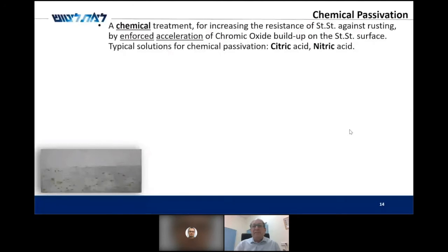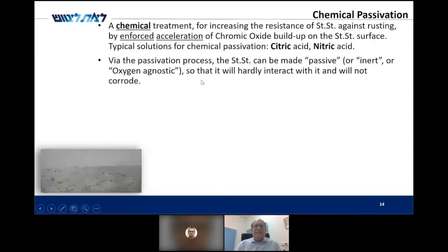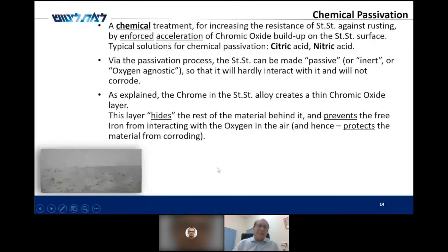So let's talk about chemical passivation. It's a chemical treatment for increasing and speeding the resistance of stainless steel against rust. We enforce the acceleration of this chromic oxide buildup using two classical acids, a very weak acid called citric acid and a strong acid called nitric acid. This passivation causes the stainless steel to become passive or inert or oxygen agnostic, so it will hardly interact with the oxygen in the air and will not corrode. And as I mentioned earlier, this is the generation of the chromic oxide. It hides the rest of the material behind it and prevents the free iron from interacting with the oxygen in the air, and hence will not corrode.